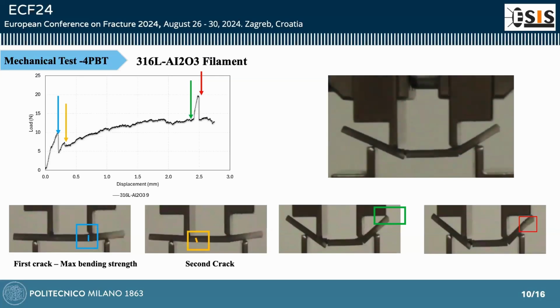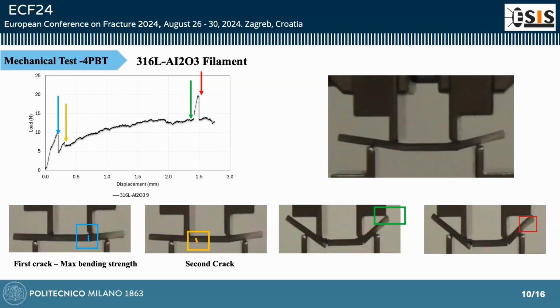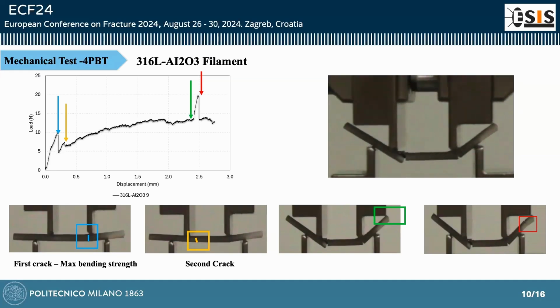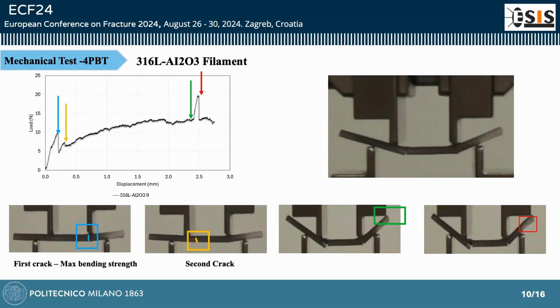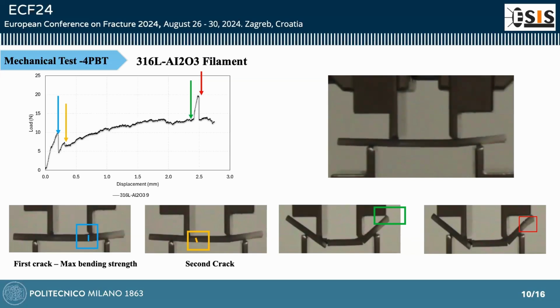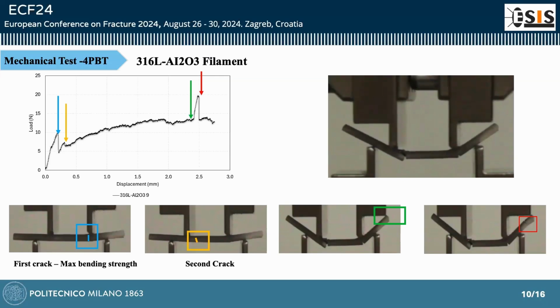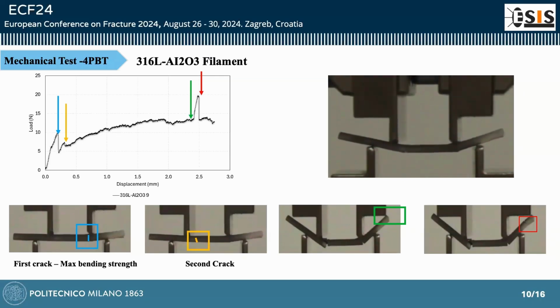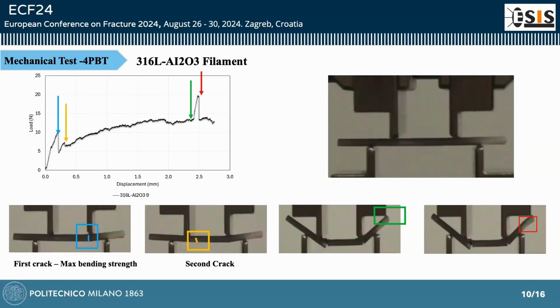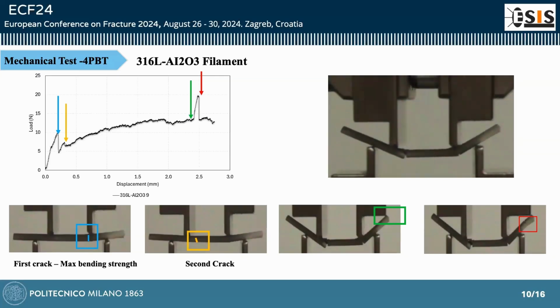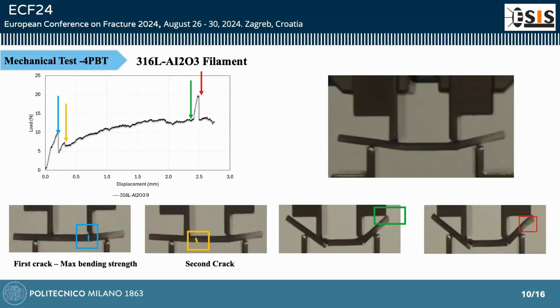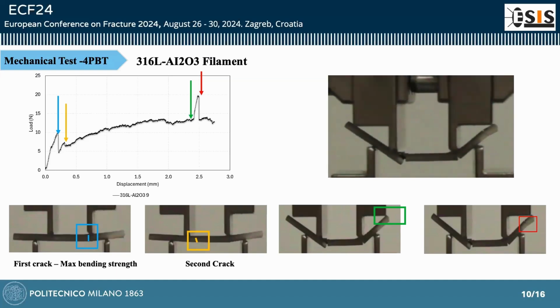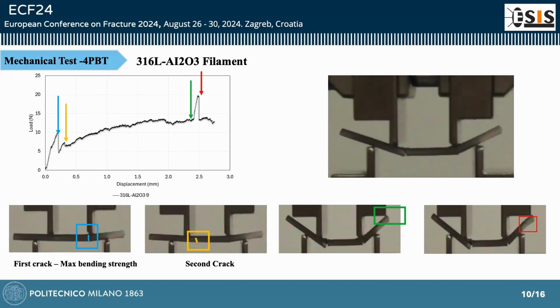In this slide, we are presenting the typical output of the 4-point bending test of the composite filament. And here we see that the first sharp drop, the blue one, is for the first crack, which is the deepest crack in the shell, I mean the ceramic part. After that, the next one, the yellow or orange one, is the second crack that is going to happen. And we see that the second crack is not going to change the trend of the curve significantly. There's also another peak at the end of the curve, which is not significant because it's due to the secondary contacts. Another point that we saw on this curve is that after the first crack, when the shell breaks, the ductile behavior becomes evident, which shows that the metal core is working.